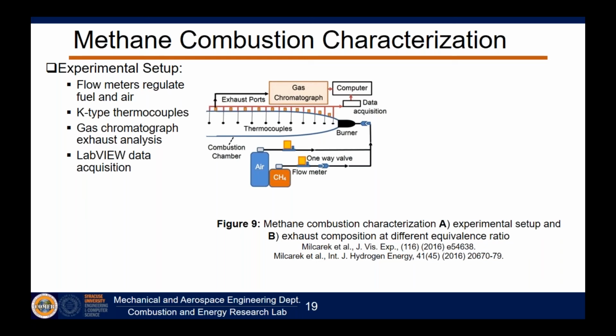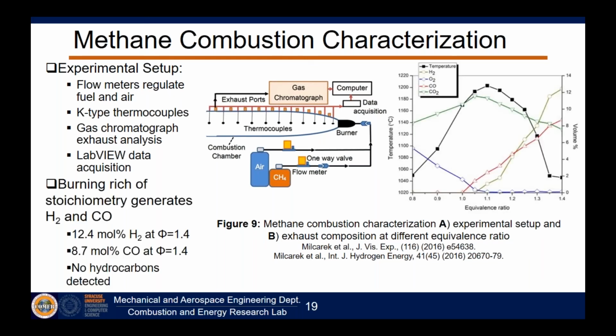We're going to send that exhaust to the gas chromatograph, which is going to analyze the composition of the exhaust, and we're going to measure the temperature with K-type thermocouples. We did that, and this isn't a very new experiment. In fact, a lot of combustion scientists already understand this pretty well, but we're building off of this as our initial starting point. And what we found, of course, 1 means stoichiometric reaction. So at an equivalence ratio of 1, we have basically enough oxygen to oxidize all of the fuel. So all your fuel should be utilized at this point. And as we see, high carbon dioxide, oxygen is essentially gone, in this case there's a little bit of oxygen left over. That's a kinetics issue, but usually it's close to 1% at equivalence ratio 1, and very little fuel remaining.